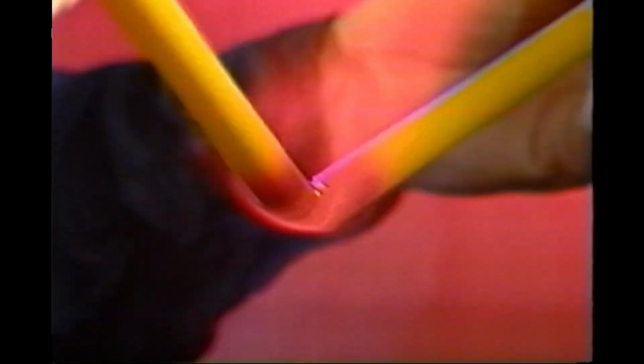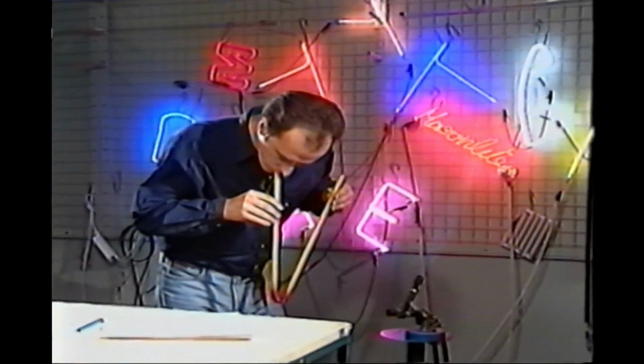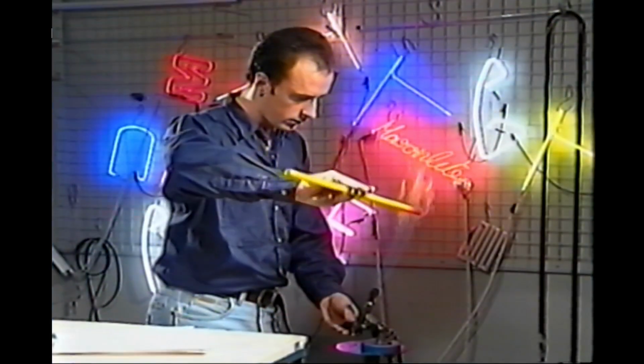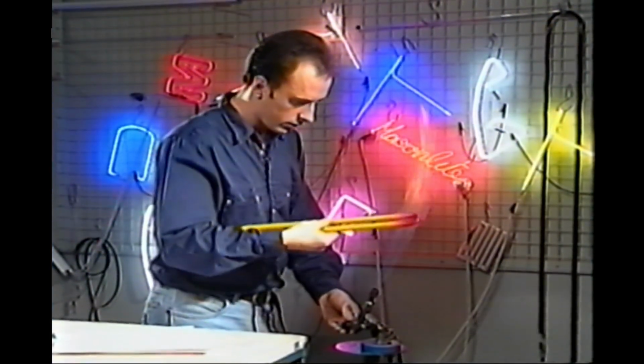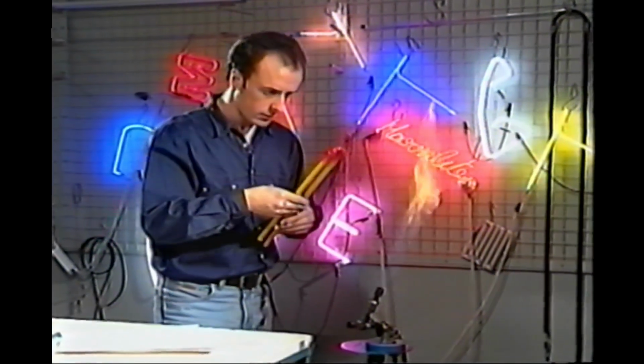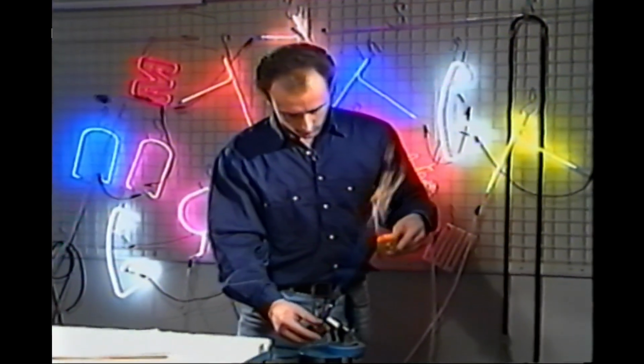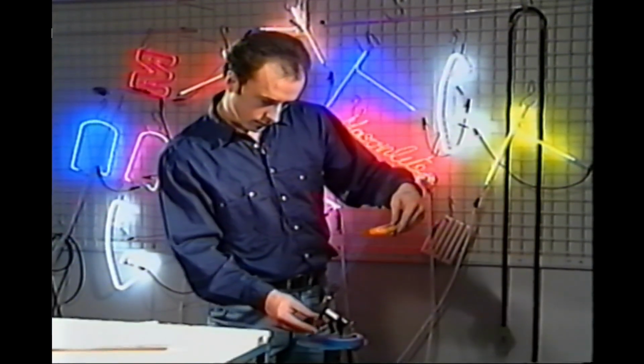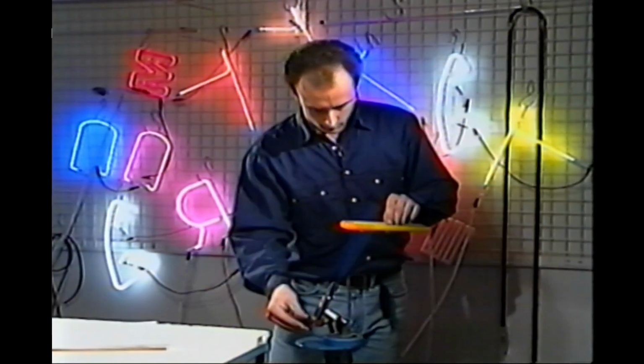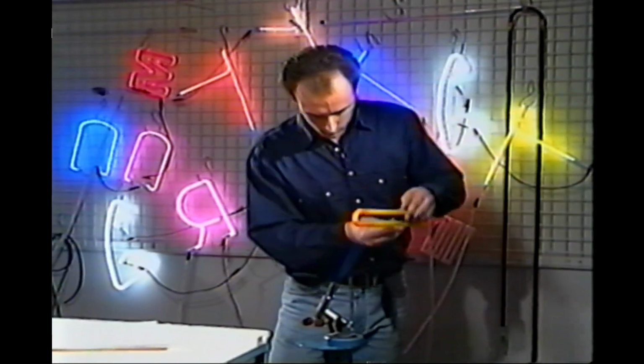Annealing of each bend must be a process added to these guidelines when colored tubing is used. The differences between lead glass and machine-drawn colored glass must be taken into account when it is being bent. Colored glass has no lead content, and as a result is a harder material requiring slightly longer melting times for each type of bend. Best results can be achieved using a more gaseous flame, ideally a flame provided by a single flame cannon burner, allowing more variety of flame types to be used.